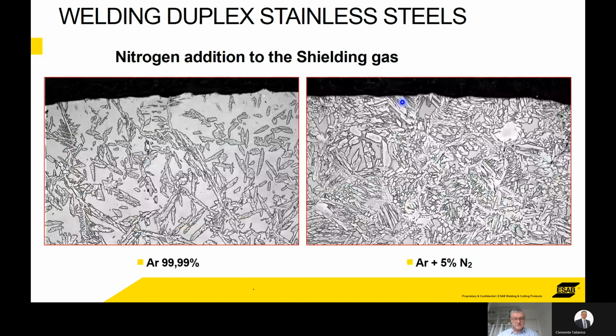These two photographs illustrate the addition of nitrogen. So you've got a pure argon shielding gas. In the surface here, none of the ferrite has turned to austenite. These dark areas here are ferrite. That means that you've got ferrite properties here, which means not so good corrosion properties, not so good strength. So in effect, it's an area of weakness. Over here on the right-hand side, we've got nitrogen in the shielding gas. You've got a lovely structure, austenite, ferrite, all the way right to the fusion line. So this is a proper duplex. It's going to have all the properties of a duplex.